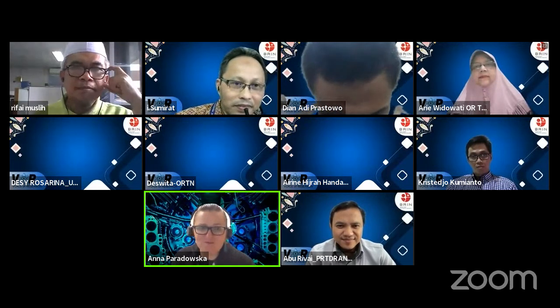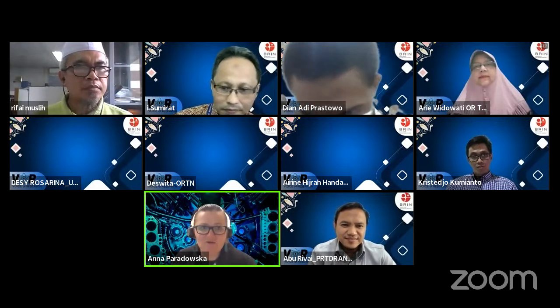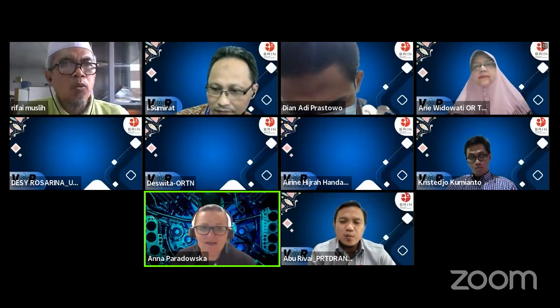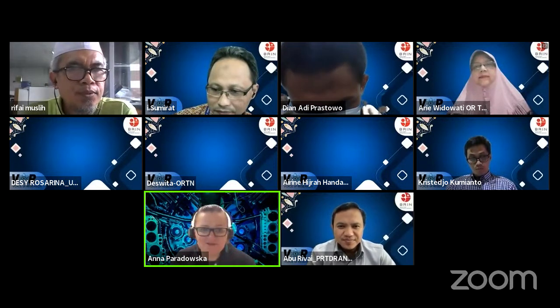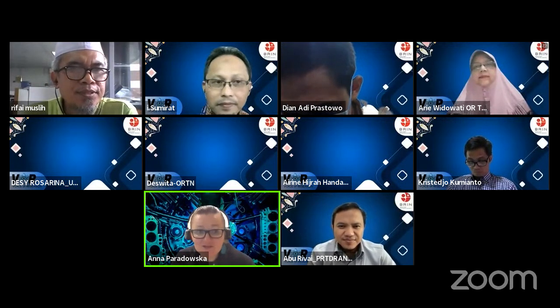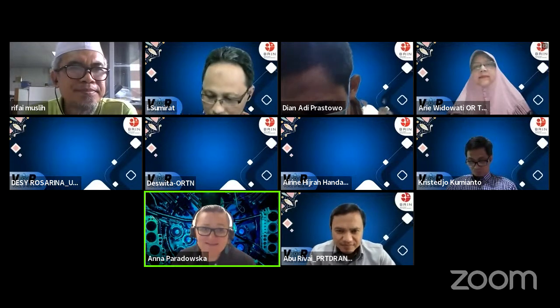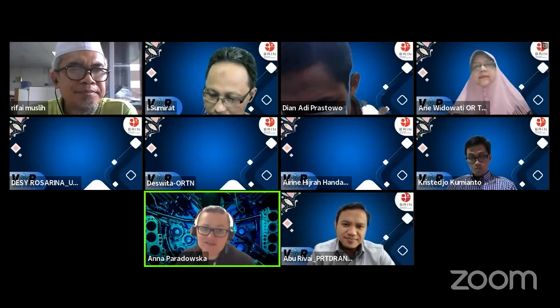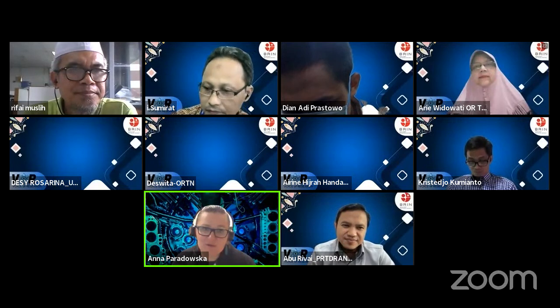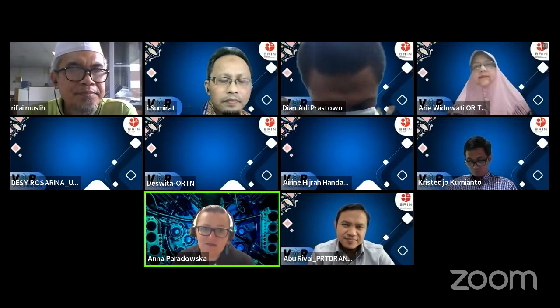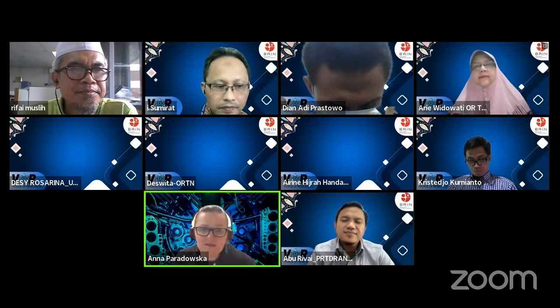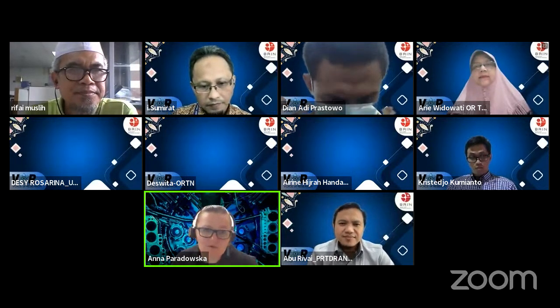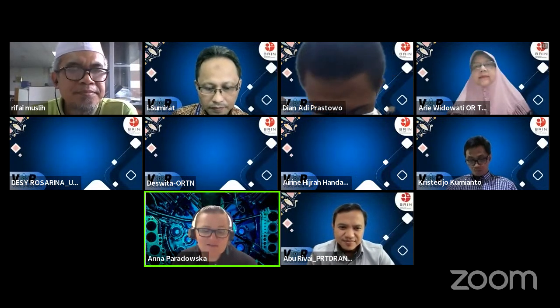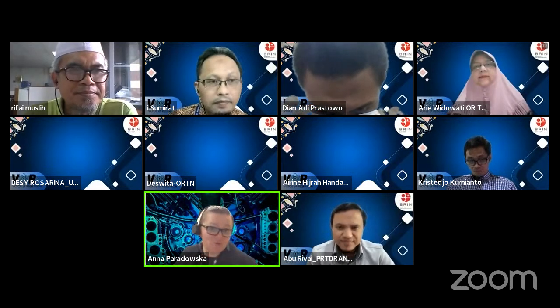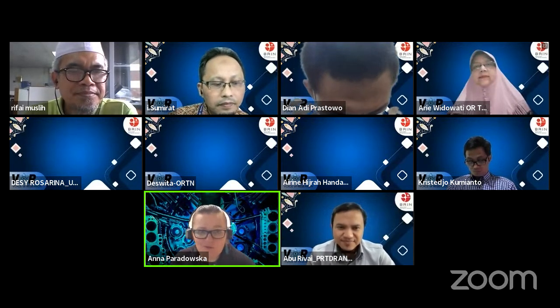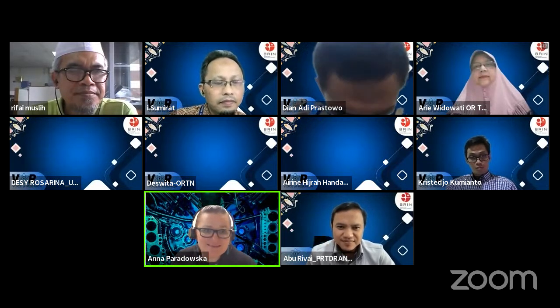Okay, so please, Prof., I start with the second question. We have a capacity of putting 1 ton on our sample stage. So we can do very large components and very small components. Our positioning stage moves plus minus 250 millimeters, and we can go half a meter below the specimen. So we can have a specimen elongated even up to 2 meters in one direction. So we look at specimens as big as 2 meters.